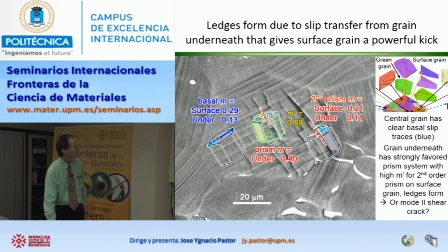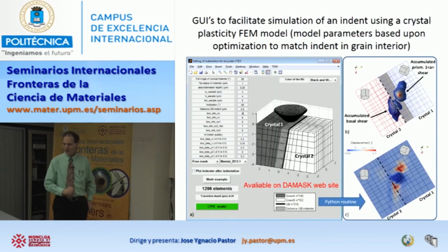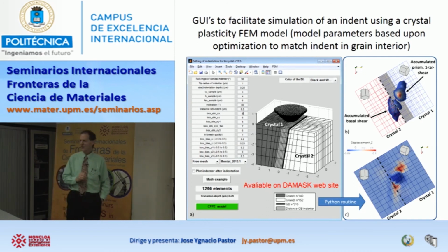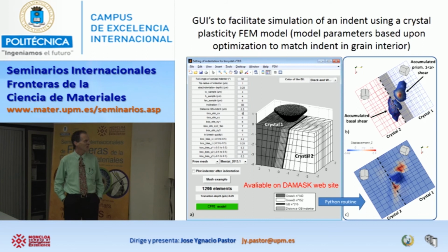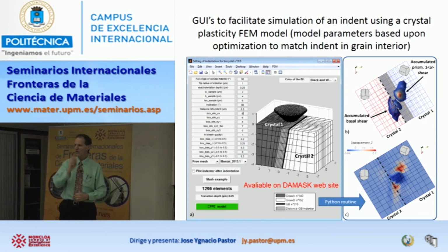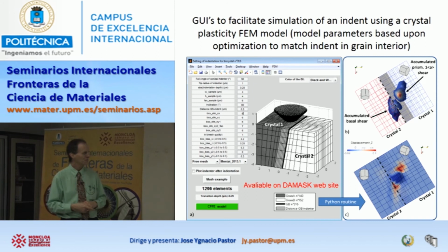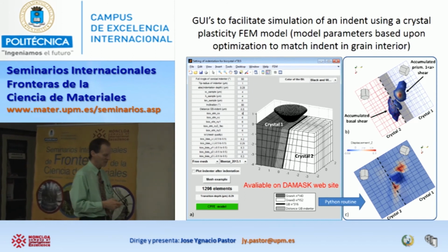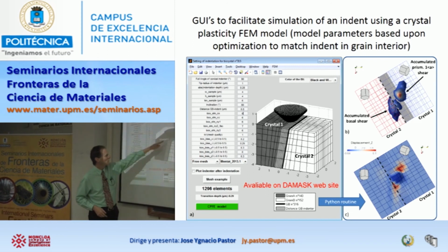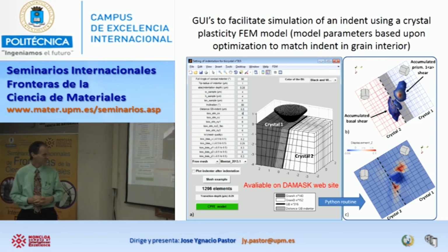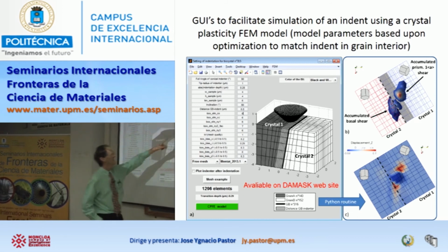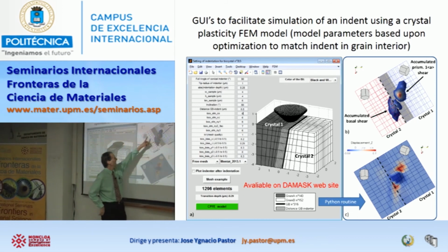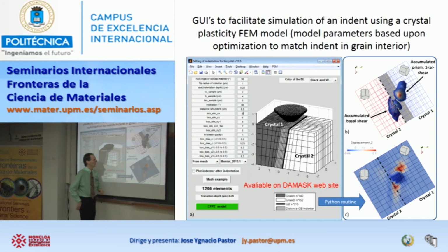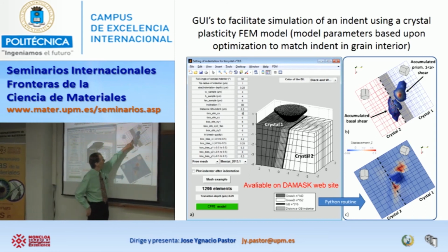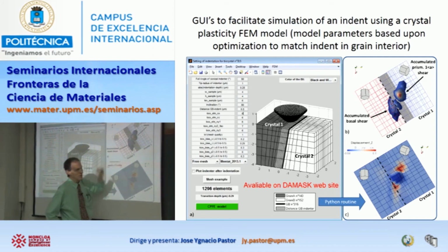Okay, well, that's the same slide, but without that other part on top. So next, I want to focus in on another set of experiments that we've done, looking at grain boundaries in much finer detail. So what we've done is we've taken nano indents and poked right next to a grain boundary. And if we do that, here's an indent right there. You can see the orientation of the crystals on either side. And we find that there is strain that has passed through the grain boundary over here.